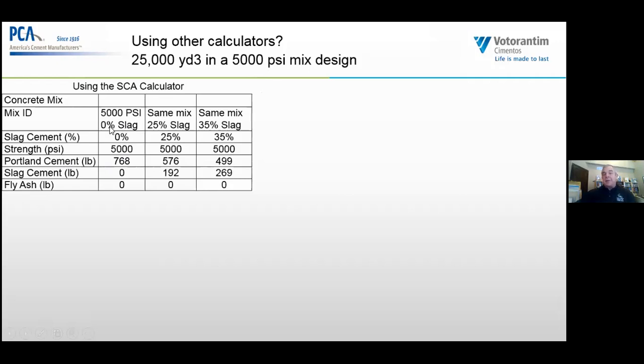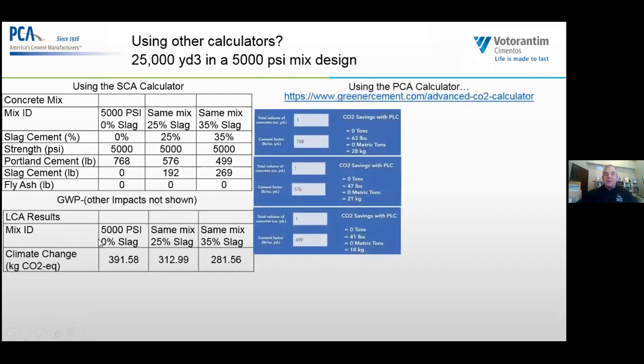So the guys asked me, hey, if I use 25% slag or 35% slag, what's my carbon footprint? And so the environmental impact, your embodied CO2 in this mix with zero slag, is 392 kilograms of CO2 per cubic meter. Oh, per cubic yard, sorry. And if you use 25% slag, it's 312 or 313. If you use 35% slag, it's 281 kilograms of CO2. We know this one already. Everybody's able to use SCMs to lower it.